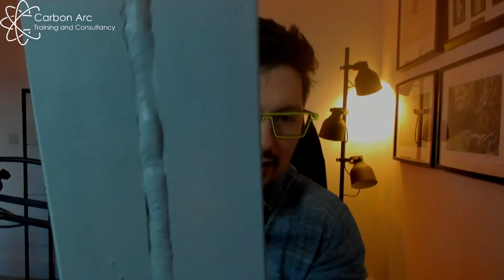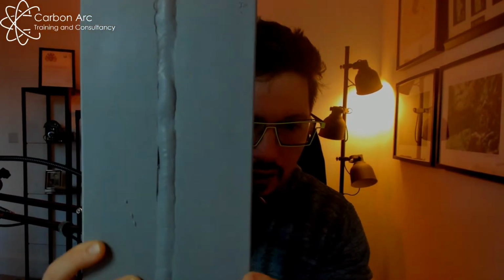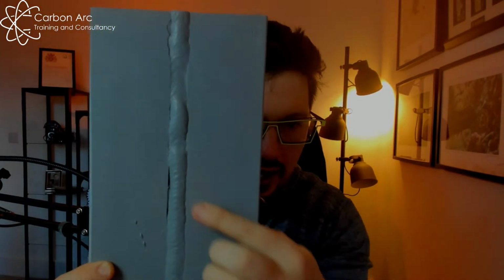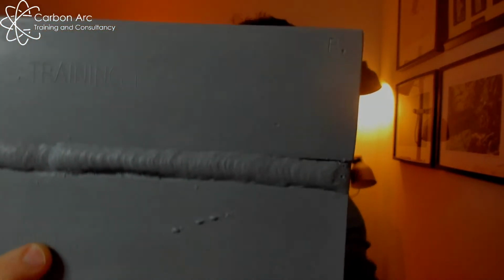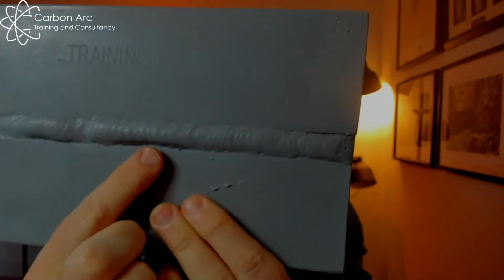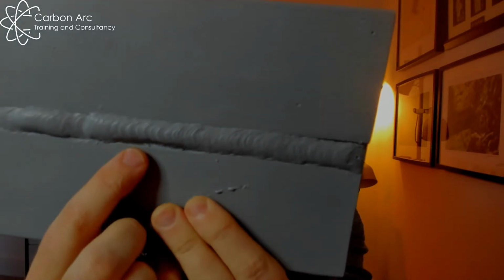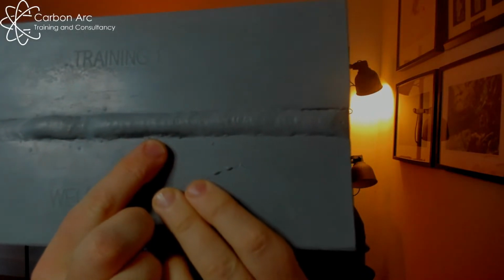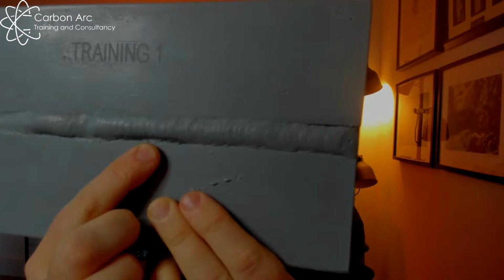If I was looking at this sample, we can sort of say, well, would I have slag coming down here? Well, yeah, look, we've got some, potentially if I can get it in the light right, this bitty material in the bottom of this weld here. You can see where it's a little bit like moving around, that's our slag. Our slag is there because it's trapped in that underfill and lack of sidewall fusion. Okay, we haven't got it out. We're probably grinding and refilling and moving on. Okay,